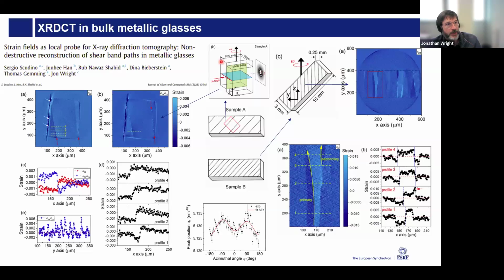And this gives you a contrast that you can see in a piece of glass where it's undergone this mechanical strain. And there's, I think, a very interesting research question of what happens when you reconstruct the component which is in the plane, which you shouldn't actually reconstruct because you're rotating the sample and you measure different things in different directions. But nevertheless, it gives a very nice picture.